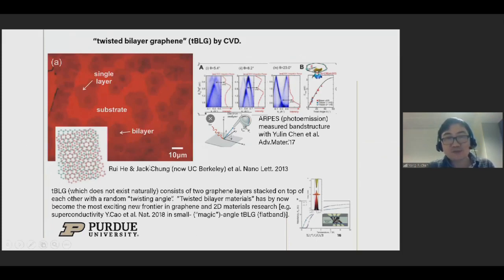A few years later, Jack Chung, a former grad student, working with a collaborator, Rui He, made a different kind of bilayer graphene. In this case, the two graphene layers have a random rotation angle. This is called twisted bilayer graphene. Here are some interesting band structures measured by ARPES, a modern version of the photoelectric effect: you shine light, and electrons kick out. This is in collaboration with Yulin Chen's group, who did ARPES measurements on some of our twisted bilayer graphene samples. And you see that when the rotation angle between the two graphene sheets becomes small, you can directly see how the two Dirac cones from the two different layers get close, and the slope gets smaller, with a very interesting evolution of the electronic structure.